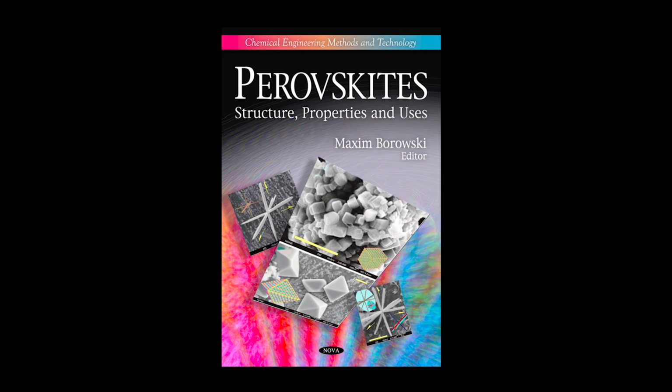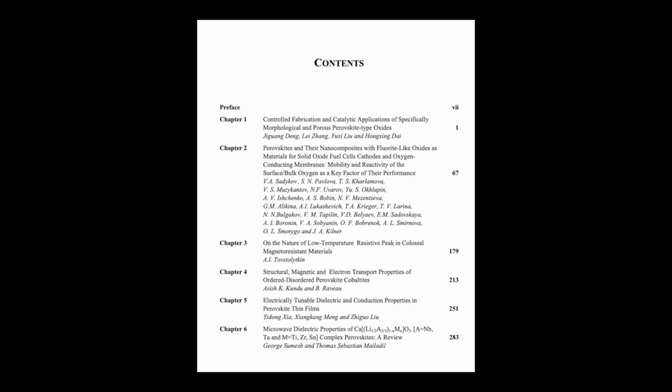So how do chemists get around that? How do they stabilize those metal precursors against this premature structural collapse during the template removal? The solution involves using advanced chelating agents or organic complexing ligands. Things like oxalic acid or EDTA are common examples. Their job isn't just to dissolve the metals initially. They chemically wrap around the metal ions, forming a highly stable, often non-melting gel or complex within the narrow pores of the template before heating. This complexing agent essentially acts like a chemical scaffolding, locking the metal components rigidly in place, stabilizing the structure.